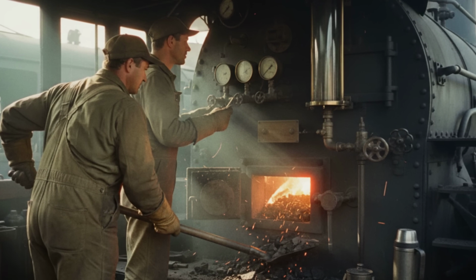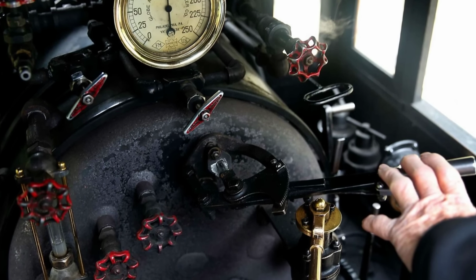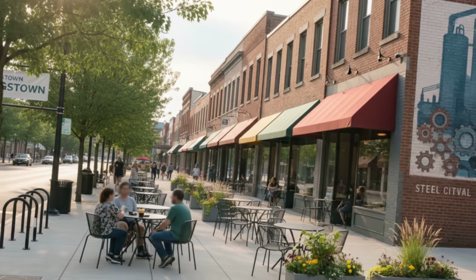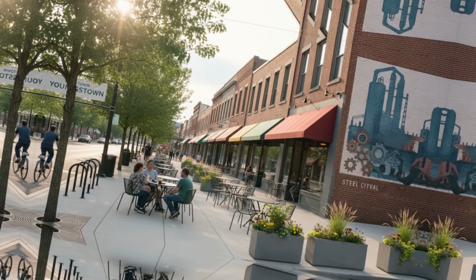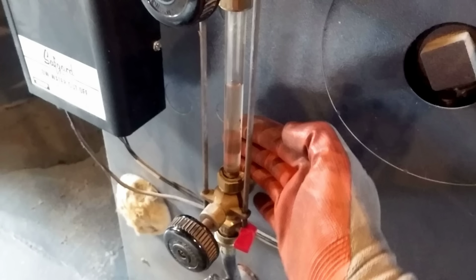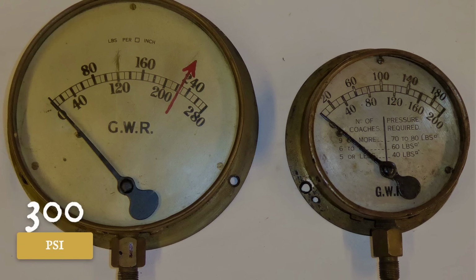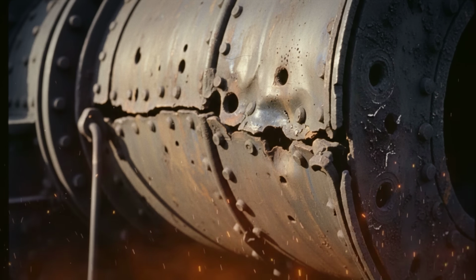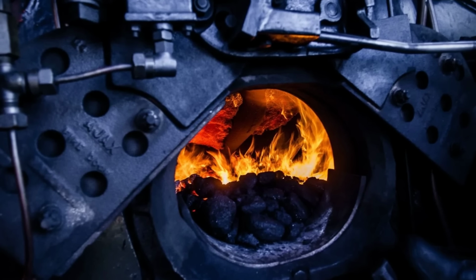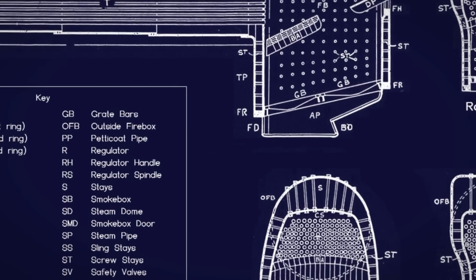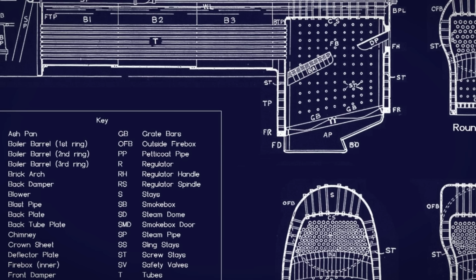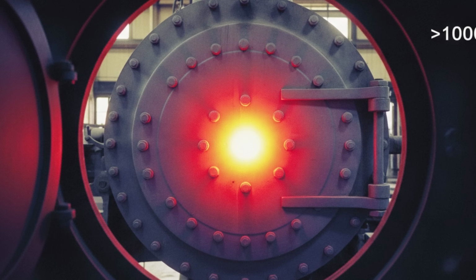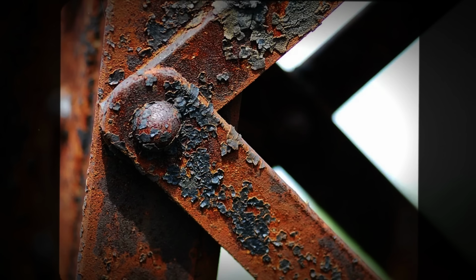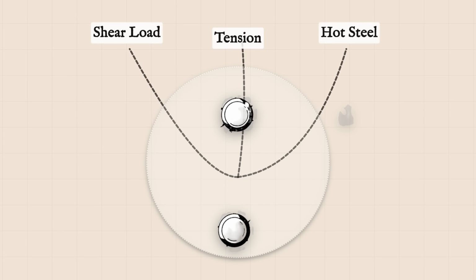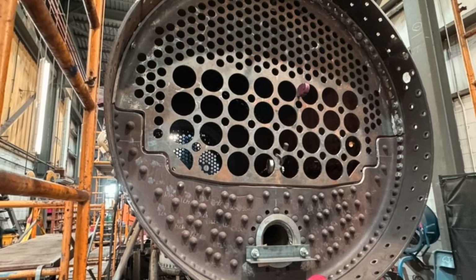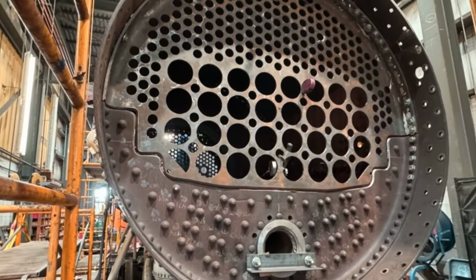The crew, operating under the assumption that routine was safety, failed to maintain the water level above the crown sheet. A clogged sight glass, left fouled by months of mineral buildup, told the fireman what he wanted to see. The true waterline was dropping. Inside the boiler, 300 pounds per square inch pressed against steel that was losing its will to resist. The firebox roared at over 2,000 degrees, and the only shield, the inch-thick barrier of water above the crown, was gone. Within a minute, the crown sheet temperature shot past 1,000 degrees. Tensile strength fell away. The stay bolts, meant to anchor the crown to the shell, began to pull through red-hot steel. The moment the last bolt surrendered, the pressure inside the boiler found its exit.